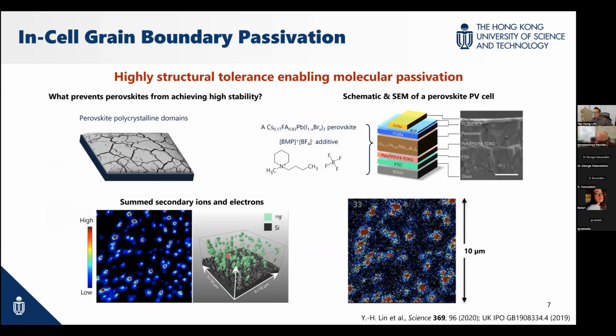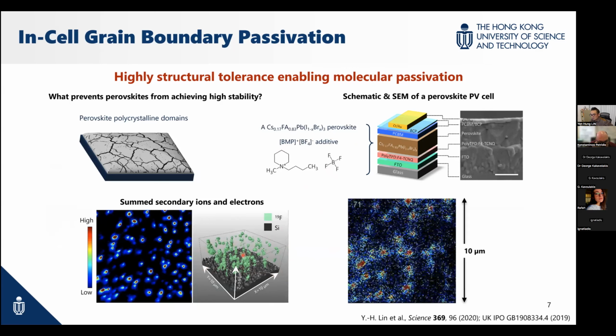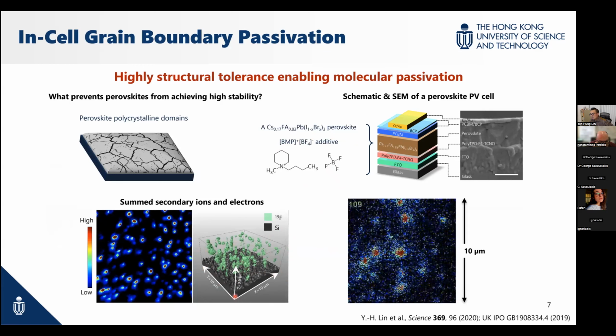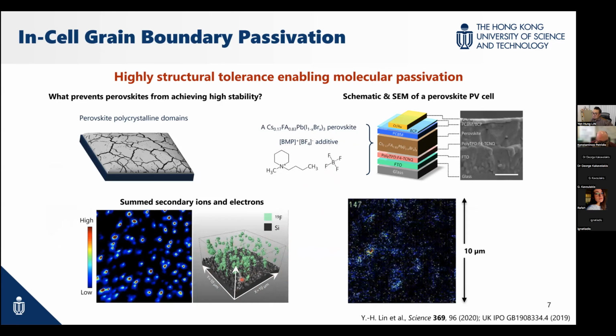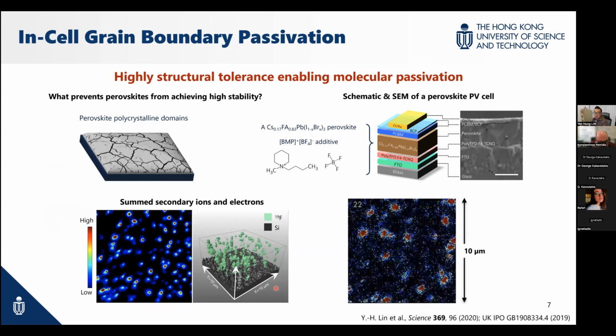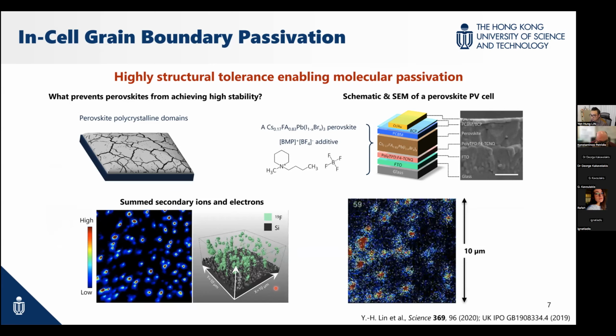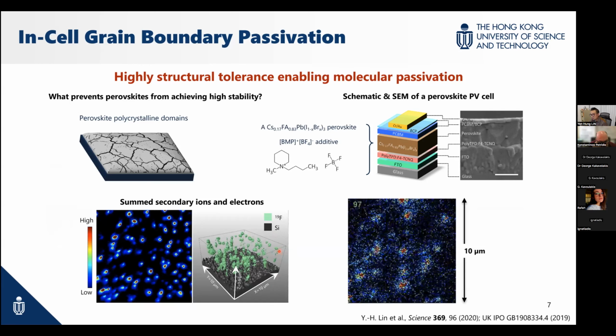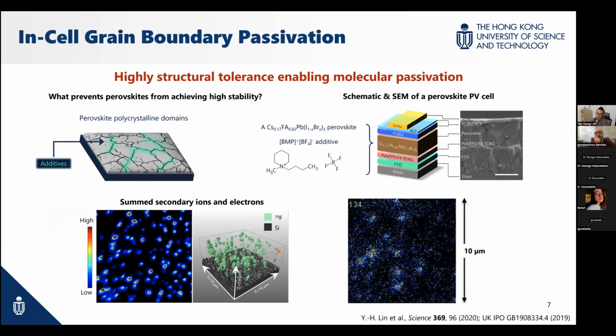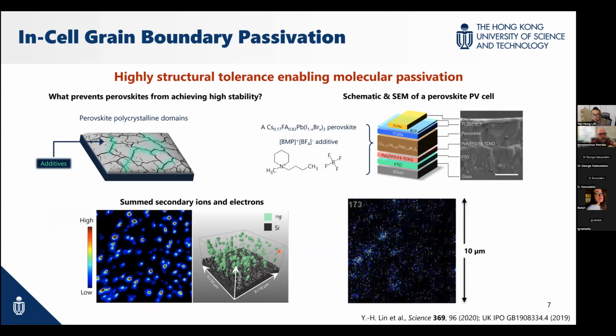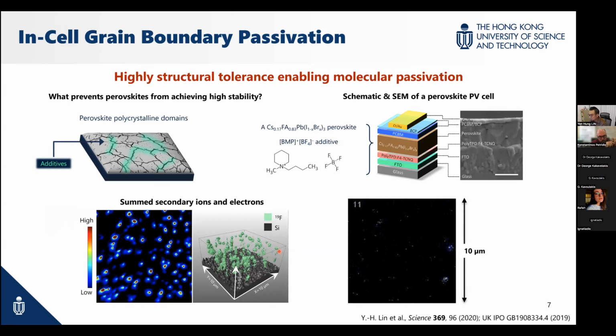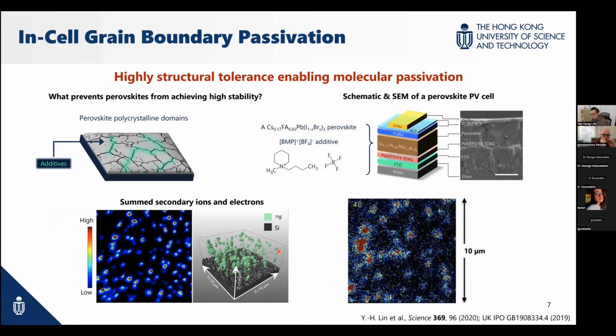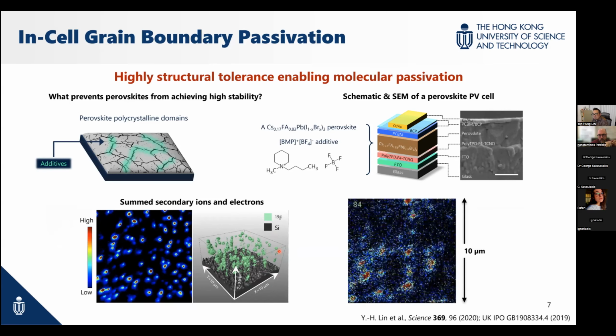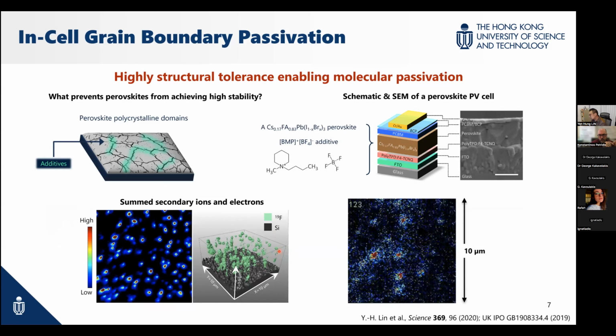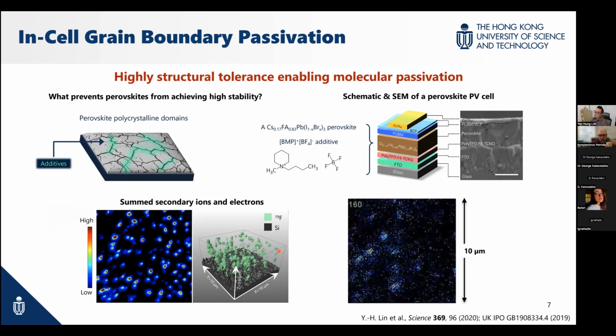You see it's a little bit lumpy here because you see cluster-like structures. But when you look at the scale here, it's only 10 micrometers. In terms of the scale we are talking about for a laboratory-made photovoltaic cell, this is quite uniform. But of course, this lumpy property indicates what we believe is the additive being pushed out to the grain boundary. This is the apparent grain boundary that we can observe by SEM, scanning electron microscope. Because as simple as that, most of the time when we add additive, it will be pushed out if the structure is too big, because it doesn't incorporate into the perovskite structure.